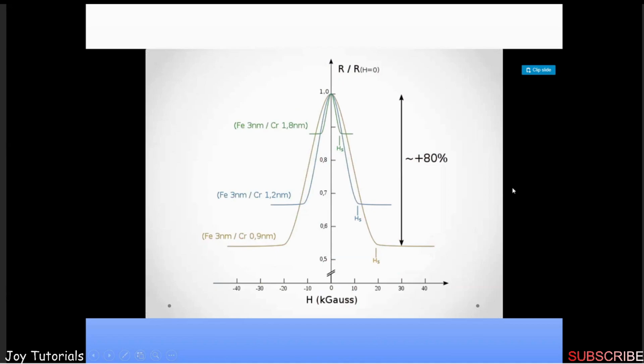This is the first GMR experiment, from Peter Grunberg's group. This is the iron, chromium, iron structure. What you see here is a structure of two thin layers of iron, 3 nanometers thick, with an even thinner layer of chromium, 0.9 nanometer, which means 9 angstrom, or 10 to the power minus 10 meter. They saw a change of around 60-70%, even 80%, if you have a chromium spacer layer down to 0.9 nanometer.